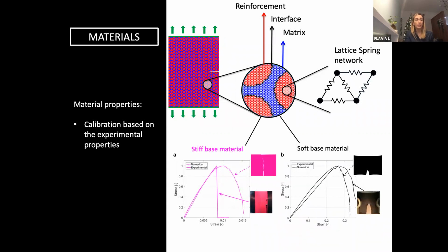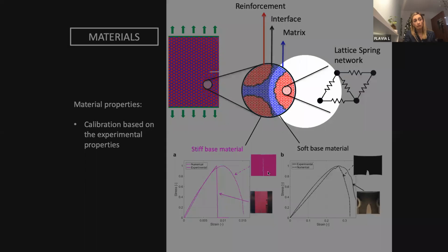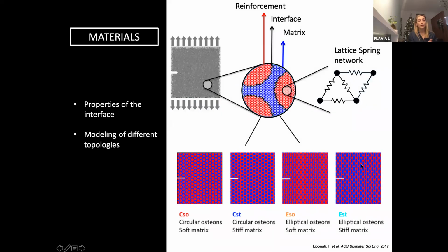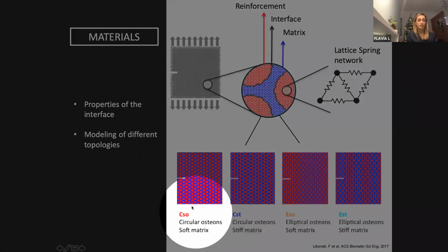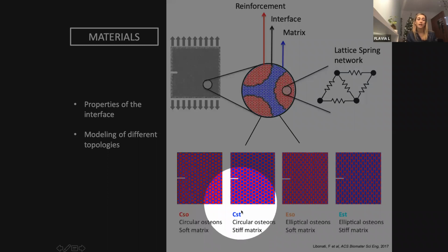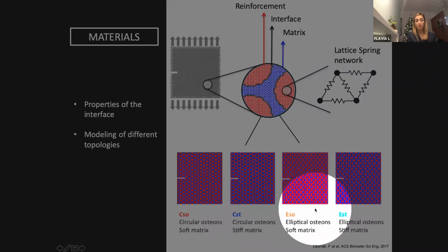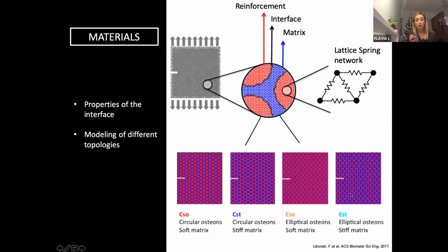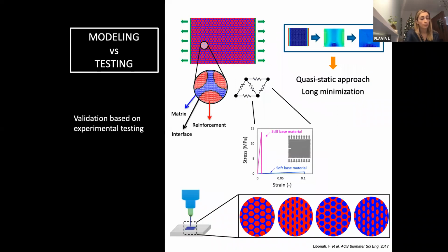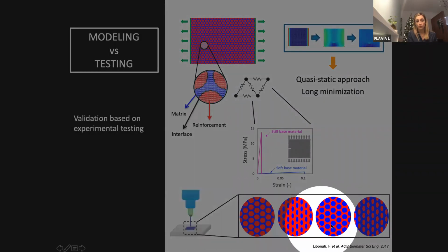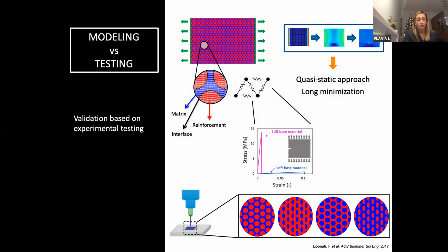So we first did a calibration on these basic materials, and we can also see a comparison between the experimental and numerical curve. And then we implemented all the designs that we previously 3D printed. We basically have a circular osteon in soft matrix, then the reverse case, in stiff matrix, and then the elliptical one in soft and stiff matrix. Of course, the elliptical one is very anisotropic, so it was studied in both directions. So basically, all the materials that we also 3D printed, we could, in the end, validate with these models.